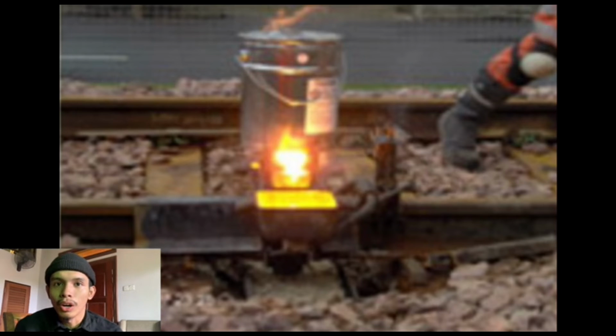Fourth, on completion of the preheating, the container is fitted to the top of the mold. The portion is ignited and the subsequent exothermic reaction produces the molten thermite steel. The container incorporates an automatic tapping system enabling the liquid steel, which is at a temperature in excess of 2500 degrees Celsius, to discharge directly into the well cavity.